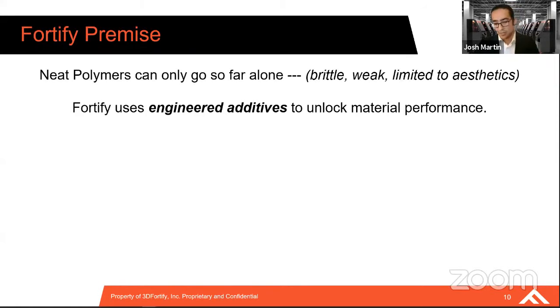And so that's really the premise here at Fortify, that neat polymers will only go so far. And if we want to provide a step change in performance beyond what's currently available, we believe that engineering additives are the way to get there, or at least one way. And this is really drawing from the conventional materials supply chain that we have now. If you look at a glass-filled nylon, for example, for an injection molding compound, it's almost twice as strong and stiff for high performance applications. And so how do we leverage that?